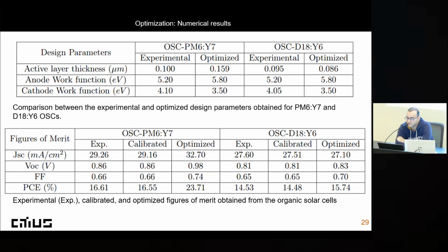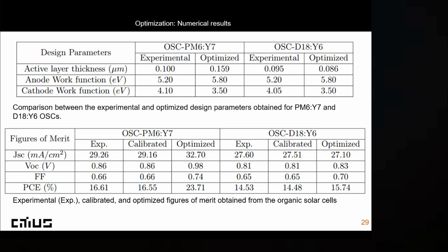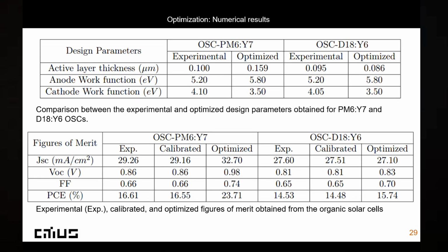For the first organic solar cell, I can improve from 16.5% to 23.7%, which is an increase of 7% efficiency, which is a lot. And for the second one, we increased the efficiency from approximately 14.5 to 15.7.